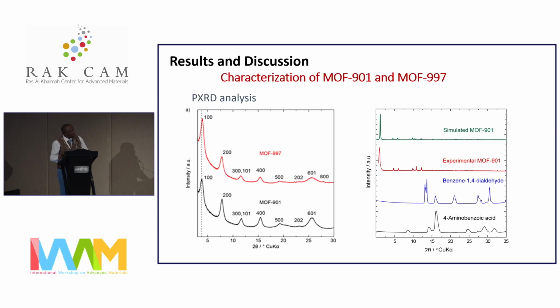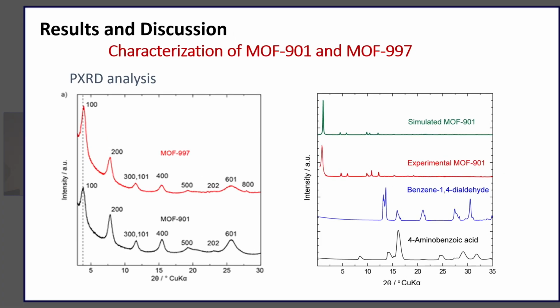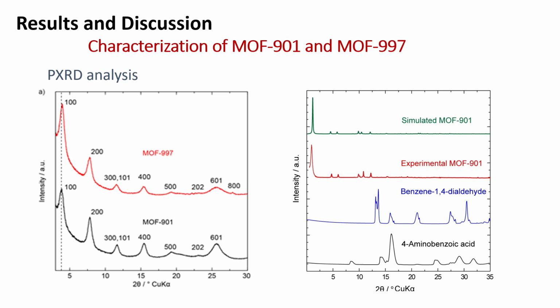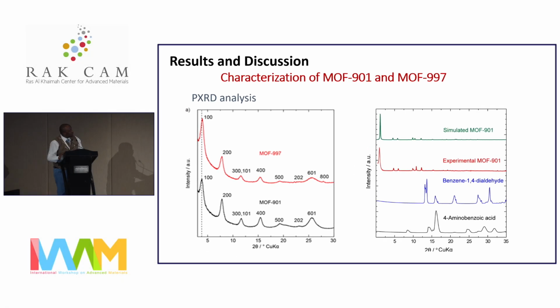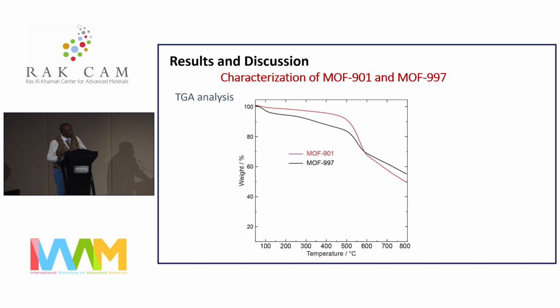Of course, starting with the synthesis, we were able to successfully make the 901 metal organic framework that agrees with both the simulated data and also the published data in literature. And when we did the oxidation using oxone, we were able also to maintain the crystallinity of the structure of the MOF, and there was just a slight shift to the right for the oxidized MOF that we named MOF 997. That showed that we did not disrupt the integrity of the MOF.